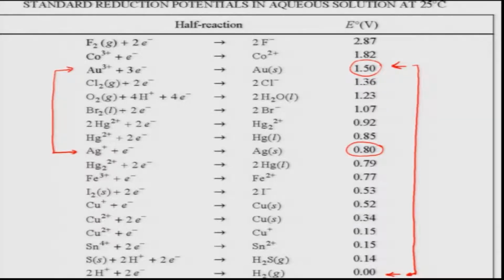So, this is the usual route of making nanoporous gold, because once we have a combination of gold and silver, the active component would become silver. So, silver would dissolve, and since gold has a very high standard reduction potential, it would try to get reduced or it would try to stay back.